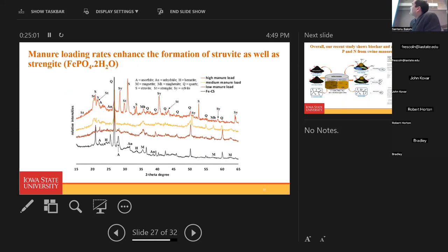In the next slide, I'm showing another XRD that we did in a different way. We took the biochar and used different manure loads: low, medium, high. In that case, we found another mineral called strengite, which is iron phosphate. We also found struvite here, but we found strengite as well. We can infer from these observations that, since strengite formation needs an iron to phosphorus molar ratio of 1, maybe here we have supplied enough phosphorus to the iron to form the strengite mineral. So there are two different scenarios for how we can process the manure with the biochar. If we want to stabilize the phosphate onto the iron phase, maybe we have to use a different manure load with the biochar.